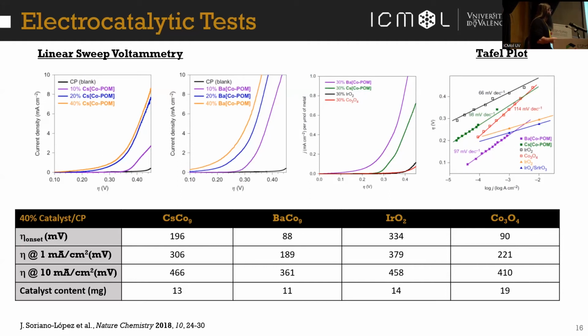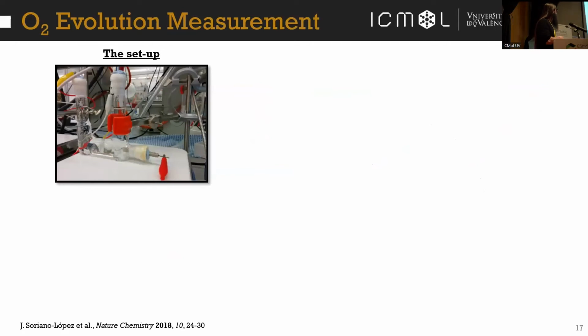Then we measured the oxygen directly from this cell. This is an H-tube in which we have the anode and the cathode separated by a porous frit, in order to avoid the crossing and recombination of the gases, and this should be very tight. And I really hate these measurements because they are a real nightmare. So yeah, we cried a lot during these measurements.